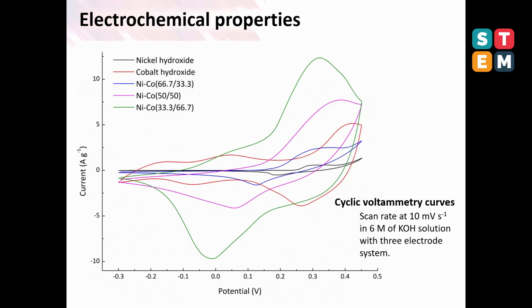For the electrochemical properties, the cyclic voltammetry curves of all ratios exhibit paired redox peaks. The result confirms the redox reaction of the active materials with the electrolyte when the working electrode was charged and discharged. Moreover, nickel cobalt hydroxide at 33% nickel and 67% cobalt exhibits the largest curve area. This implies this ratio is the optimum point of nickel and cobalt content. It also has the highest specific capacitance.